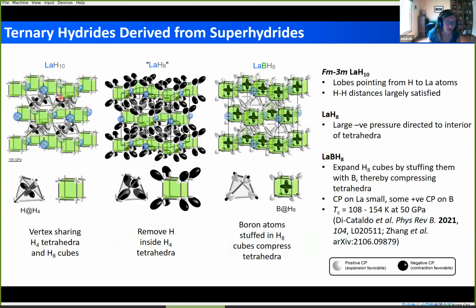I'll show you very quickly another thing one can do using this chemical pressure approach: identify regions where you could put another stuffing atom. For example, in lanthanum H10, if you take this atom out of the structure, we note that you would like to compress the tetrahedra, which you can do by adding a boron to the tetrahedra, relieving the chemical pressure in the system.